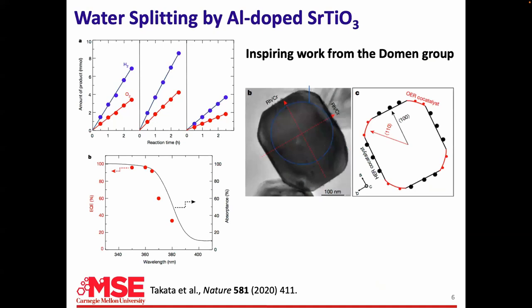This paper came out about four years ago. This axis is the quantum efficiency of water splitting, this is the wavelength of light. In UV light at about 365 nanometers, this is 100% — within experimental error, 100% efficiency. Even if it's only 95%, we're not going to do any better than this. The only problem is there's not a lot of 365 nanometer light that makes it to the Earth's surface, so overall efficiency is about 2% of total sunlight. But nevertheless, that this can be done is amazing.